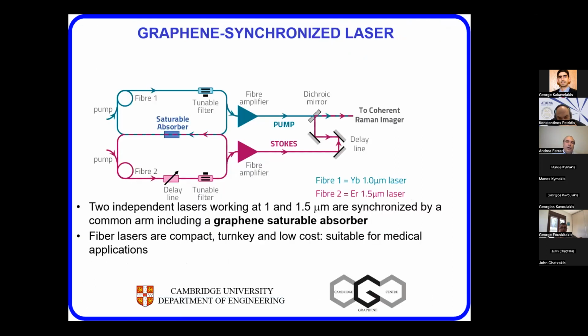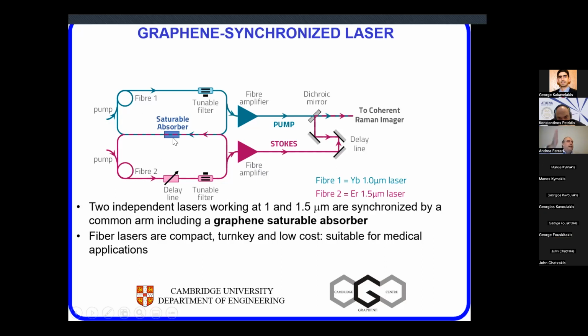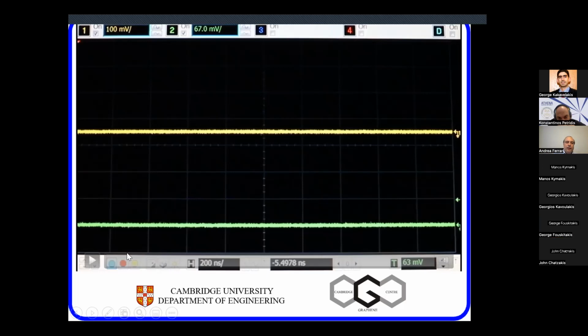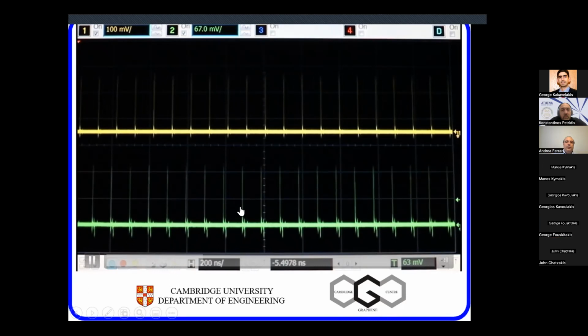So what we were trying to do a few years ago is to prove that the same piece of graphene will work at different wavelengths at the same time. So in order to do this, we had to make two lasers that had one leg in common. And in this common leg, we put the same one piece of graphene. And what happened, okay, both lasers worked, but what was seen was more interesting. Both of them became synchronized. As you see, the lasing is starting, and after a few passes, you see both lasers are completely synchronized.